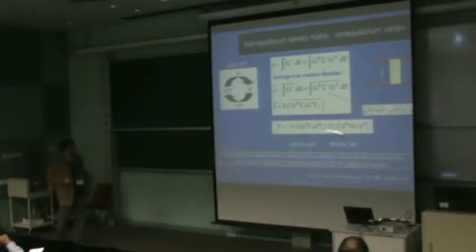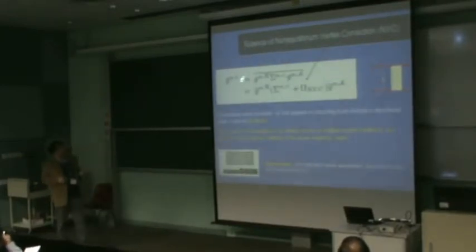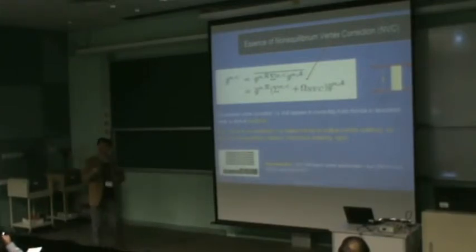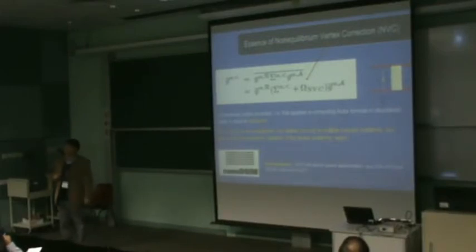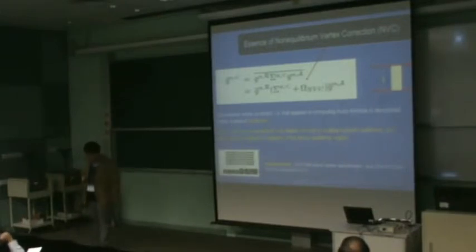You get them beautifully. You can see from the formula that you have an electron with Q coming in and Q going out, and this one is Q coming in with Q prime going out. So you have this momentum non-conserving component due to disorder scattering, and you get it very physically. By doing these kinds of things, you will be able to derive a set of formulas that you only have to calculate once. The mathematical essence is to break this average of the forward propagator and backward propagator with a self-energy that you have to calculate. This self-energy is done on the complex contour, the non-equilibrium contour. It's reminiscent of dirty metal theory in solid state physics. But nevertheless, everything is reflected; the statistical information is also reflected here.